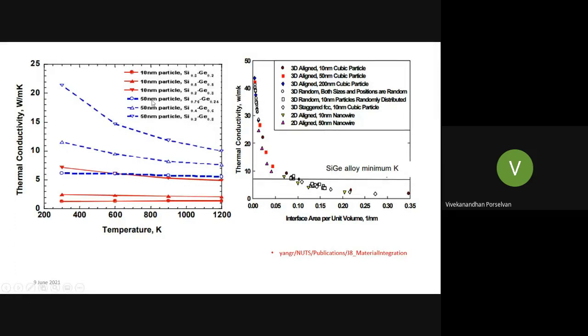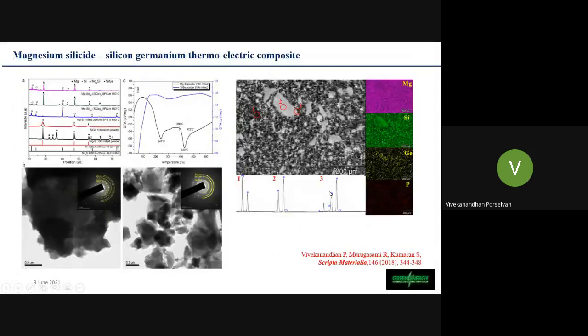So we can see that as the particle size is reducing, there is a drastic reduction in the thermal conductivity. It is one of the accepted phenomena, you know, that as the particle size is reducing, that is, as the scale is reducing, it significantly favors the reduction in the thermal conductivity. The similar case is here.